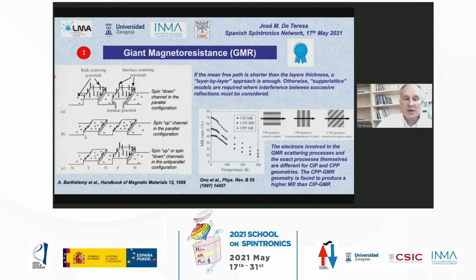So this is what would happen for conduction electrons with a spin down or a spin up, for example, in the parallel configuration. So for the spin down channel, it will see on the ferromagnetic layers a high potential because the exchange interaction will make this high potential appear. And also there are interface scattering potentials. So at the interfaces, there are normally defects that will affect the resistivity a lot. And also in the inner part of the layers, you will have what are called bulk scattering potentials.